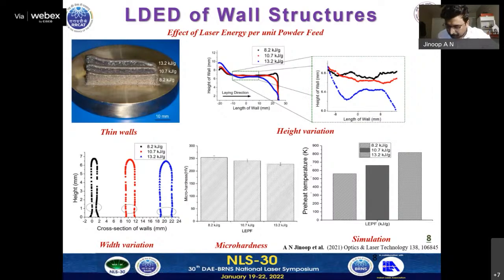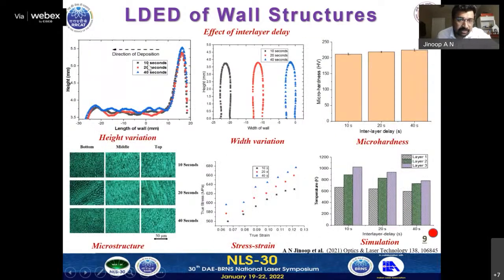Further, we did another study where we varied the idle time between the layers. The idle time is varied between 10 seconds, 20 seconds, and 40 seconds, and we studied the effect of this parameter on the geometry, microstructure, and mechanical properties. We could see that the geometry had not much variation, but more stability is achieved at lower interlayer delay, mainly because of the higher thermal stresses at higher interlayer delay values.